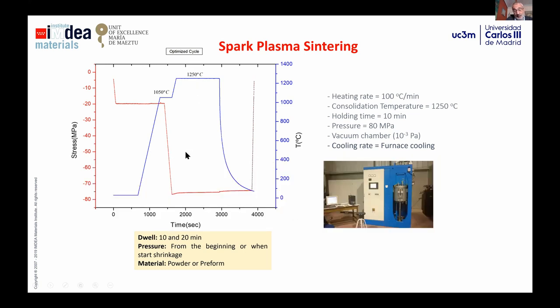As you can see in this typical cycle, you can reach in the order of 1250 degrees in a very short time, and the dwell time for reaching the best properties in this material, to have full density, is in the order of 10, 15, 20 minutes. So if you compare with hot isostatic pressing, in which you sometimes need more than 2 or 3 hours to reach full density, at the end you have a way to get advanced materials while controlling the microstructure and the grain size much better with such methods.